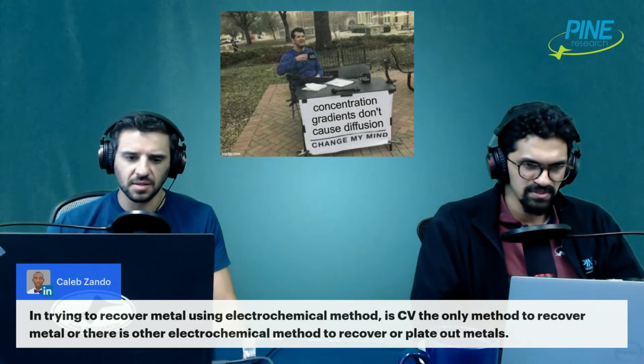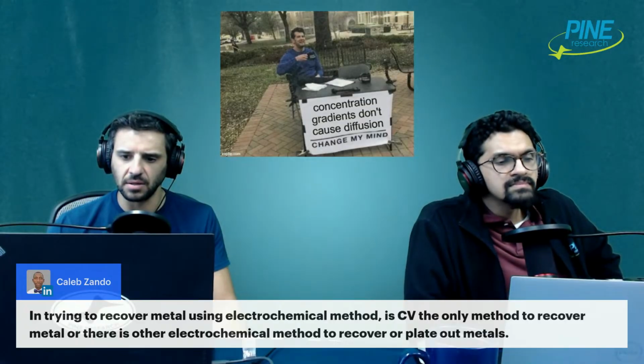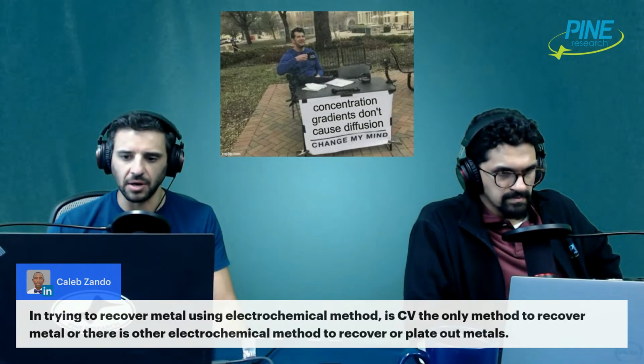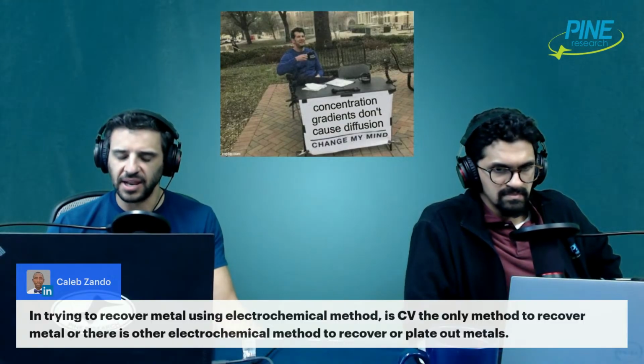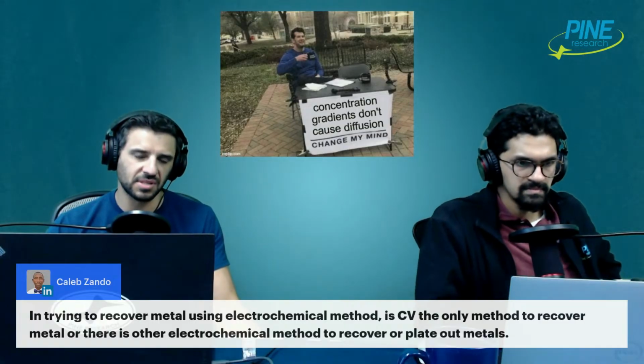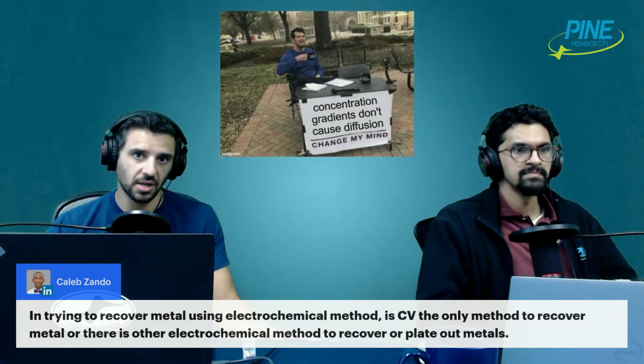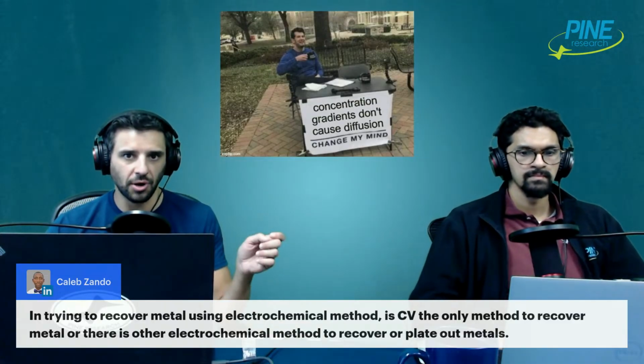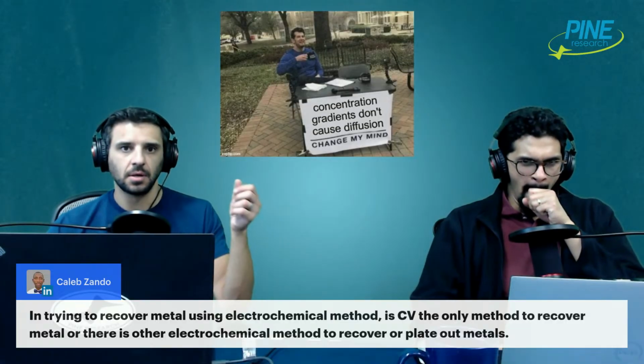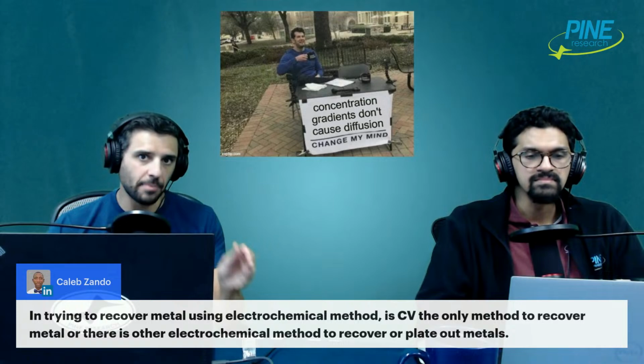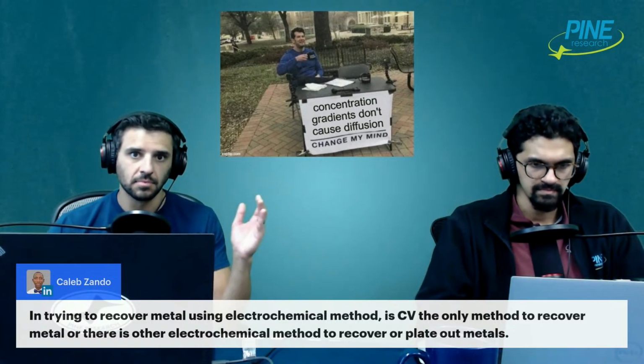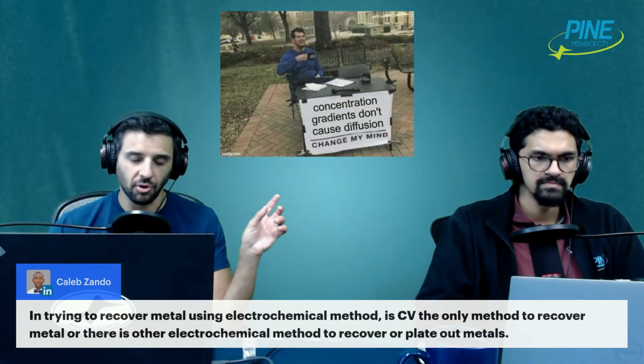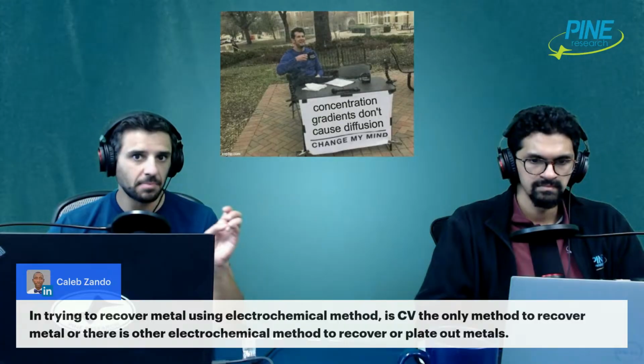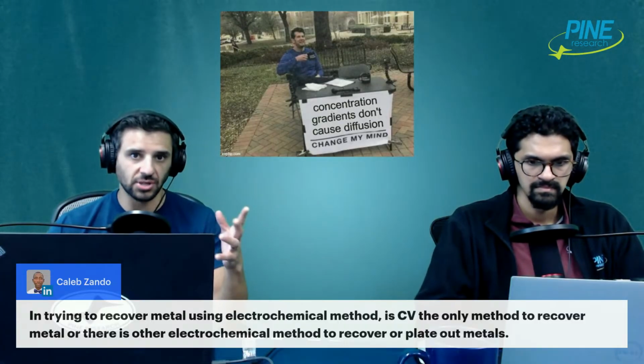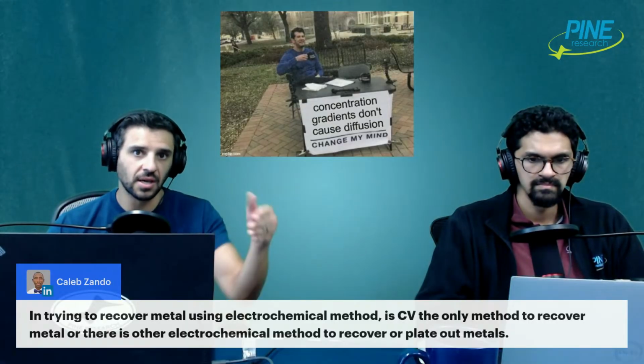All right. So Caleb is from LinkedIn. Thanks for joining us on LinkedIn. He says, in trying to recover metal using an electrochemical method, is CV the only method to recover metal, or is there another electrochemical way to plate out metal? No, you'd probably want to use either constant current or constant potential, which would be called chronoamperometry or chronopotentiometry. So chronoamperometry, CA sometimes: chrono, time, amp, current, metry, measuring. So chronoamperometry is measuring current over time. You're setting a potential, measuring the current over time. The other one, chronopotentiometry, CP: chrono, time, potential or voltage, metry, measuring. So measuring the potential over time. That's when you set a current and measure the potential over time.